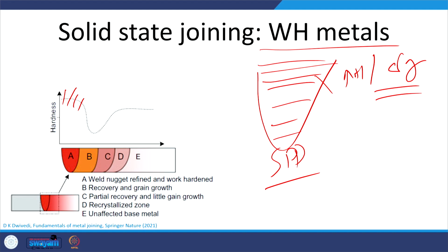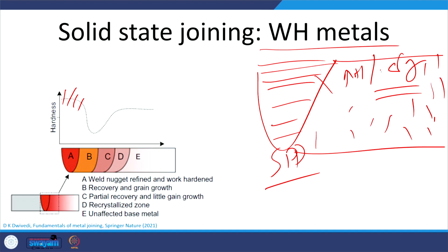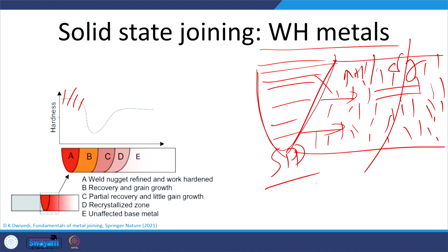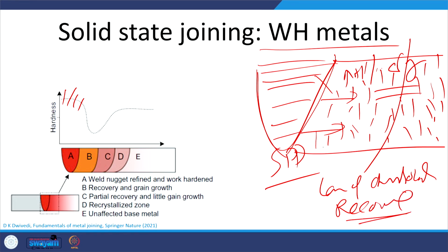Away from that, whatever zone is being formed, since work hardening metals are strengthened by the development of dislocations, through controlled plastic deformation we try to realize a high dislocation density, so that the yield strength and hardness can be enhanced. But when a solid state joining process like FSW is carried out, the heat generated during the FSW is dissipated to the underlying base metal, and that in turn causes the loss of dislocations. So, recovery predominantly occurs in the heat affected zone.